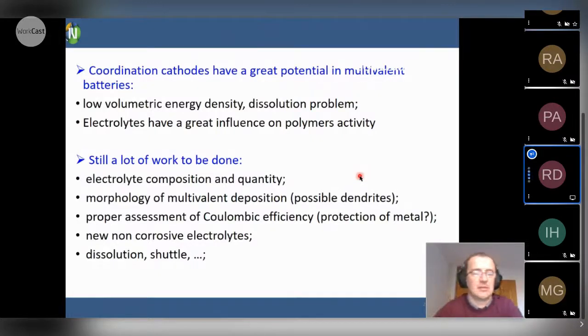So I will just go quickly through these conclusions. Coordination cathodes have a great potential in multivalent batteries. So this is important. But low volumetric energy density might not be really suitable for premium electromobility, but might be suitable for some electric cars, city-driven electric cars. The dissolution of organic moieties is still a problem and needs to be solved. And as I discussed today, electrolytes have a great influence on organic moieties' activity. So electrolyte composition and quantity matter, and we don't know what is really going on at the metal anodes: passivation of the metal anodes, morphology of the deposits, possible dendrites study.